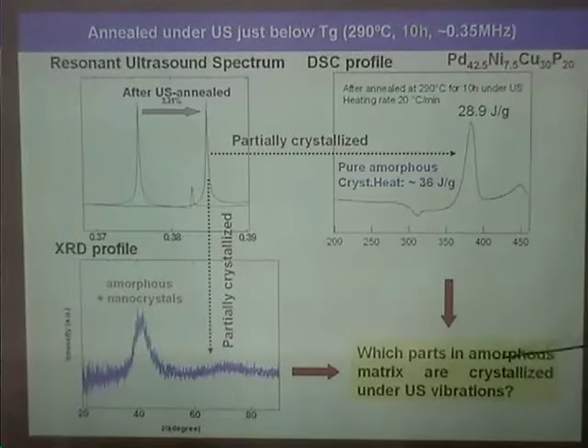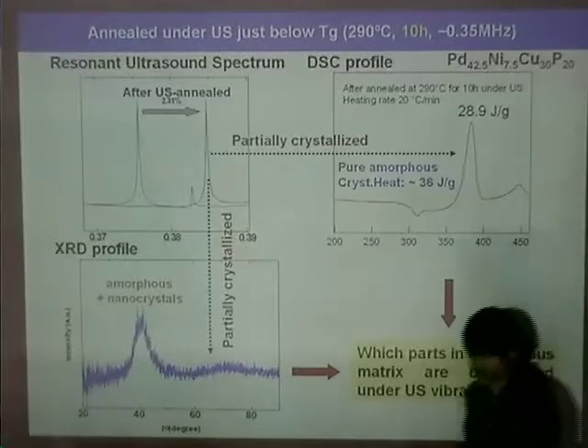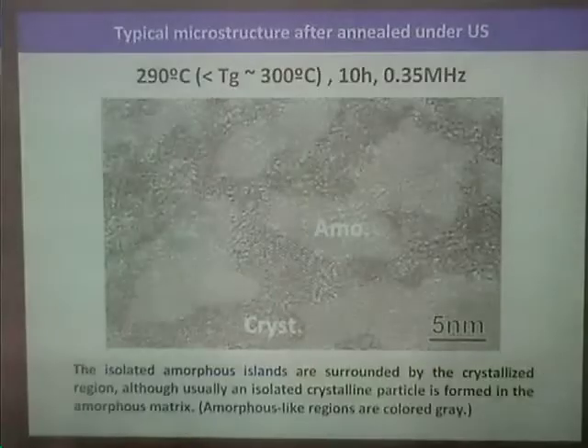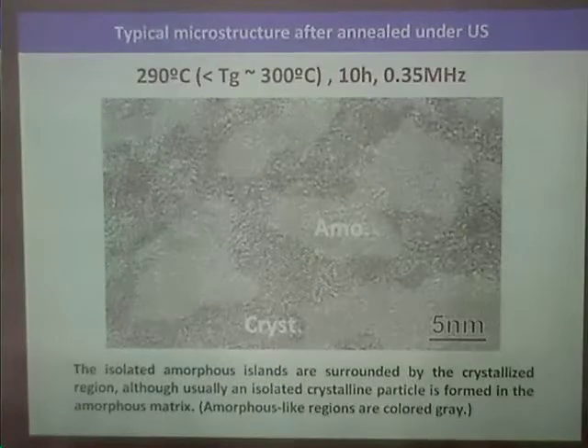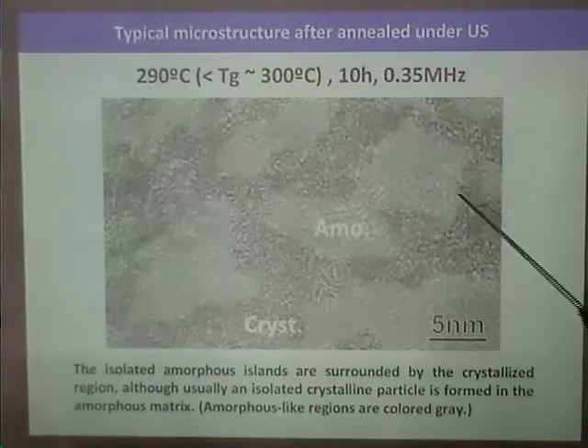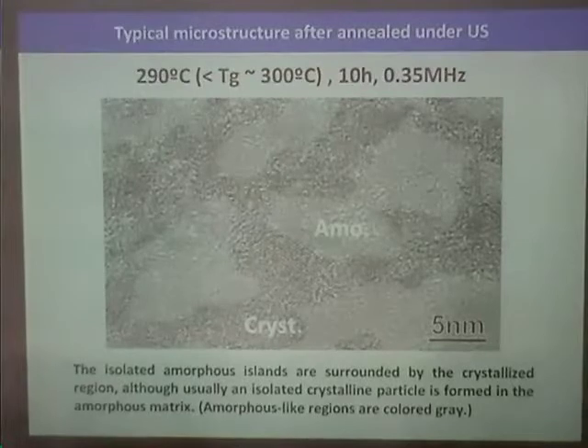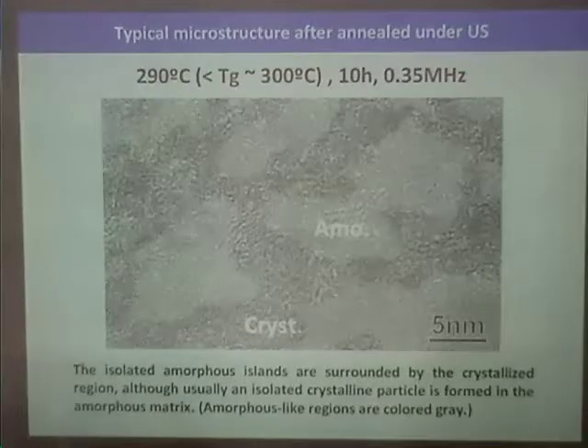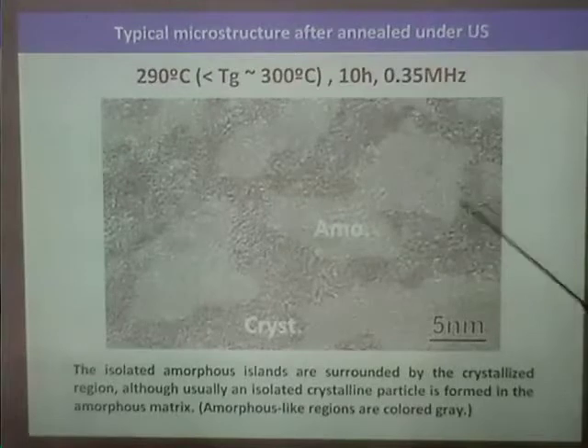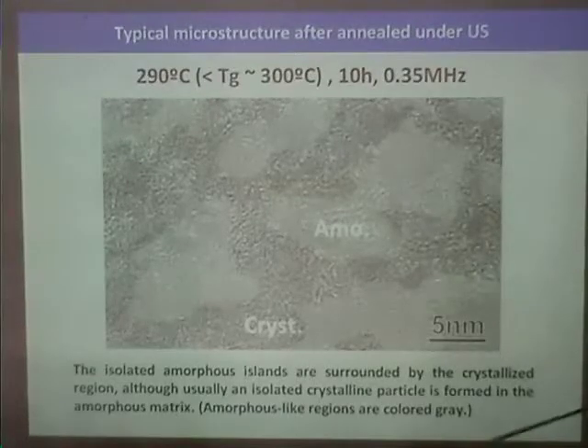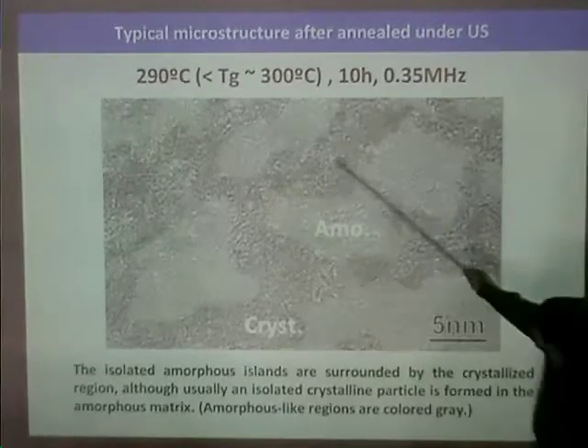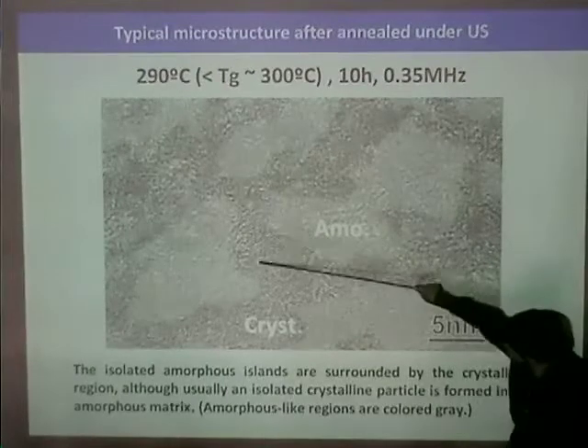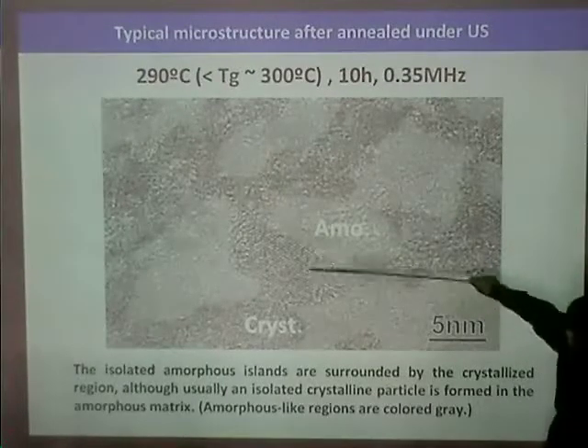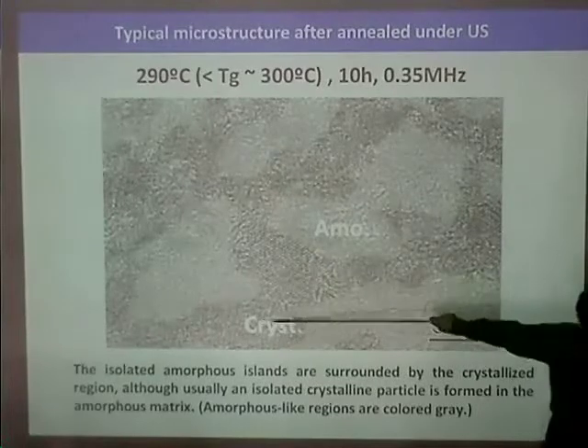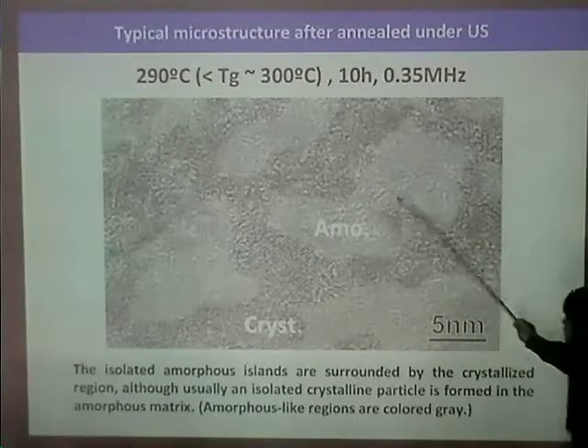Which part of the amorphous matrix is crystallized under the ultrasonic vibration? This is a very interesting question, and it is answered here. This figure is observed by TEM, transmission electron microscopy. The amorphous-like region is colored gray for visualization. The lattice contrast, the fringe contrast, indicates the crystal. But this is amorphous-like.